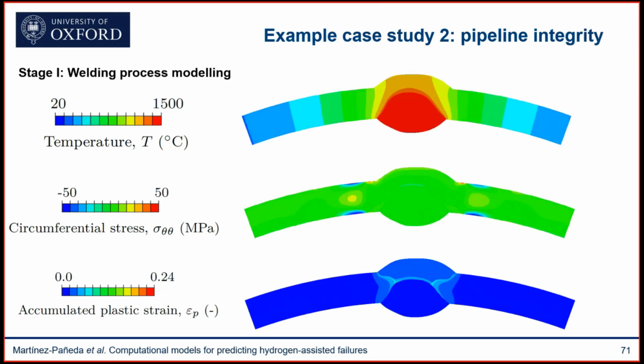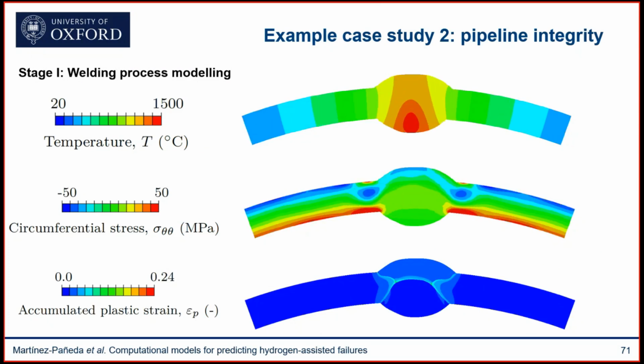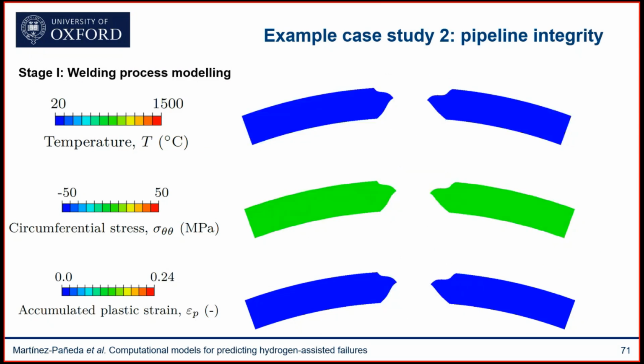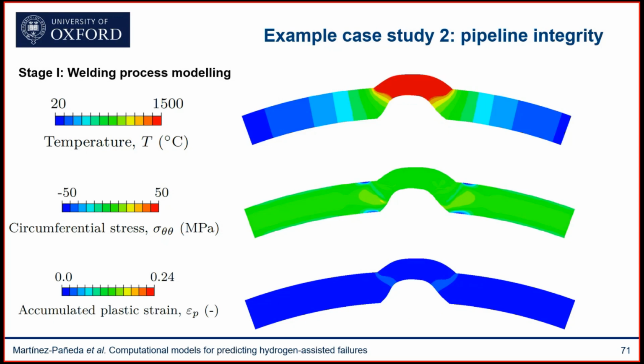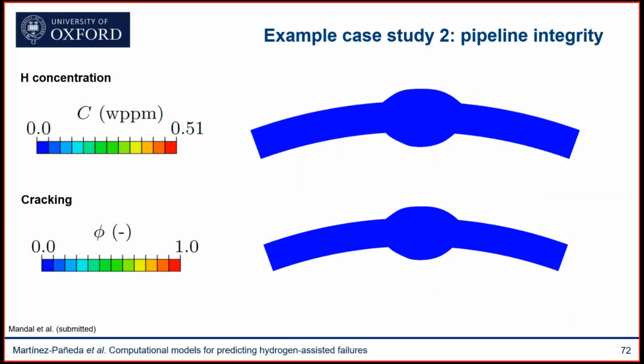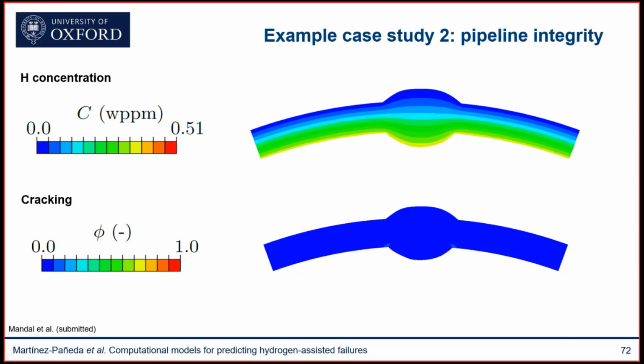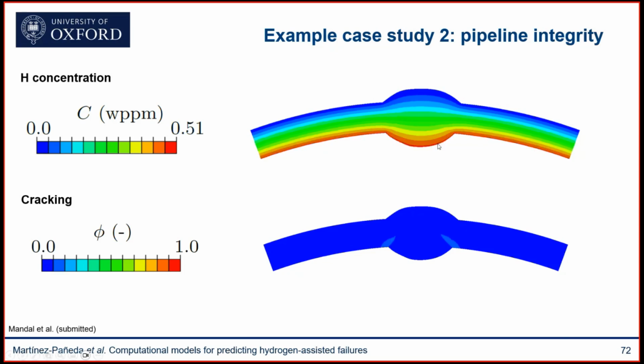So we apply a torch. In this case, this is a seam weld. It has two passes, so we can predict the distribution of the hydrogen content in there, the temperature, the stresses, and accumulated plastic strains. Then we expose that welded pipeline with those residual stresses to a rising hydrogen pressure. And you can see here on the top how the hydrogen distribution grows as you increase your hydrogen pressure. And then eventually you get this propagation of a crack.